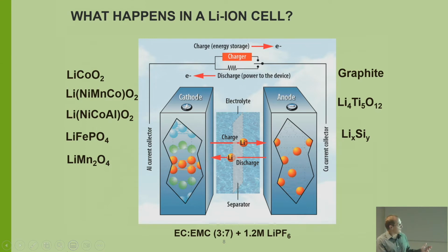So one thing you have to look at is everything's called a lithium-ion cell, but it's really a whole mixture of different options for your positive electrode. You can have any of these materials: lithium cobalt oxide, NMC, as we call it, nickel manganese cobalt oxide, then your lithium iron phosphate, your lithium titanates. Those can all be in a lithium-ion cell, usually not mixed together though. On the negative side, it's usually graphite, but you can also have some silicon in there, and once in a while the LTO as your negative electrode.